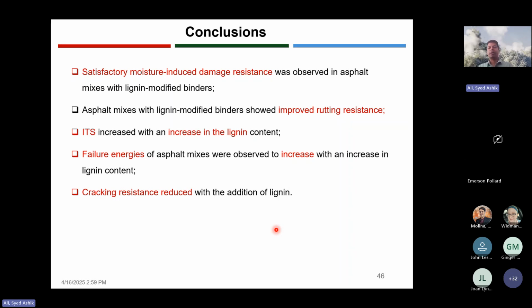Satisfactory moisture-induced damage resistance was observed from the asphalt mixes with lignin modified binder. Also, the rutting is good. ITS, indirect tensile strength, increased significantly with lignin. The cracking resistance went down a little bit with the lignin modification. So we can expect to have good moisture-induced damage resistance. We can expect to have good rutting resistance, but cracking resistance could be a problem.